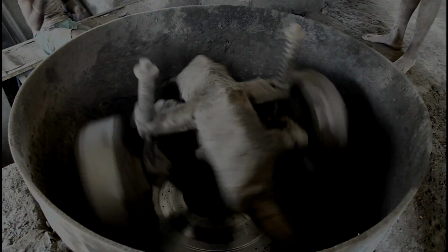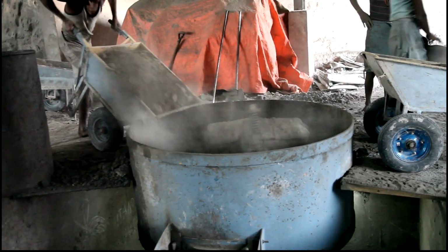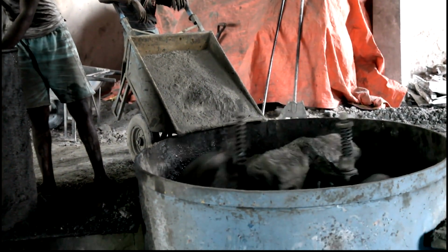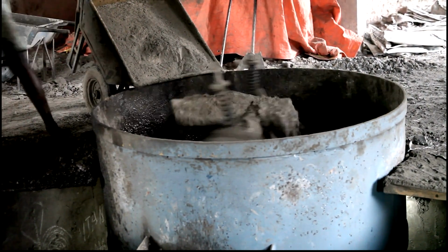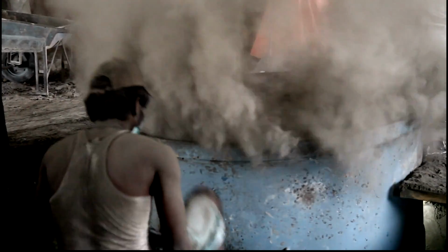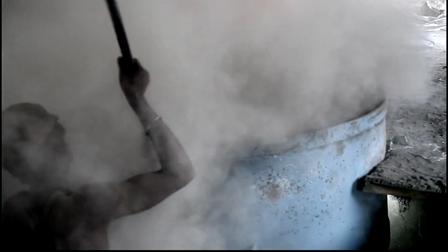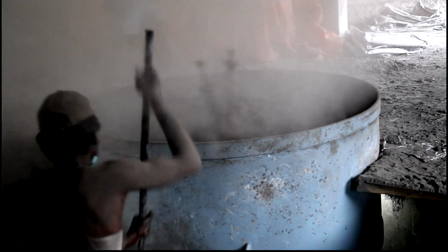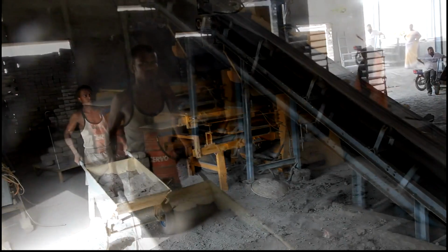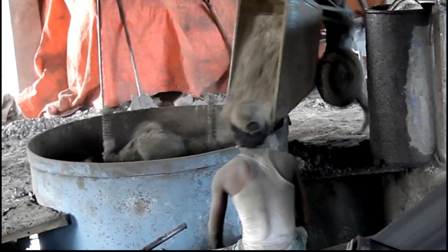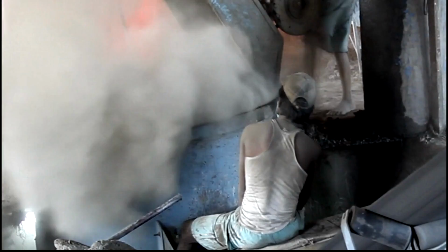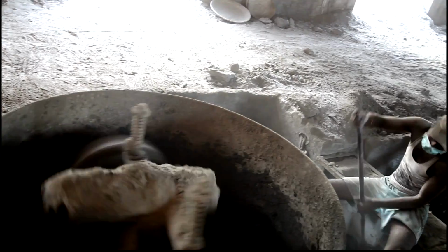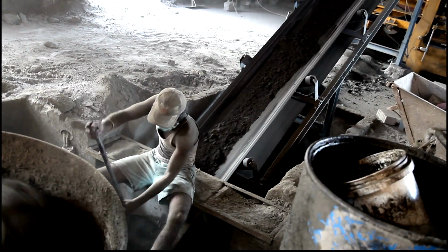A pan mixer of adequate capacity should be used for mixing and grinding raw materials. 20% of sludge lime and 5% of gypsum mixture is initially added to the pan mixer, and then the required quantity of water is added. After that, 20 to 25% of sandstone dust shall be added, along with a quantity of water. Finally, fly ash, a raw material obtained from the power plant, is added to the pan mixer along with a quantity of water. Mixing should be carried out until uniformity in color and a homogeneous mix is obtained. It will take about 5 minutes.